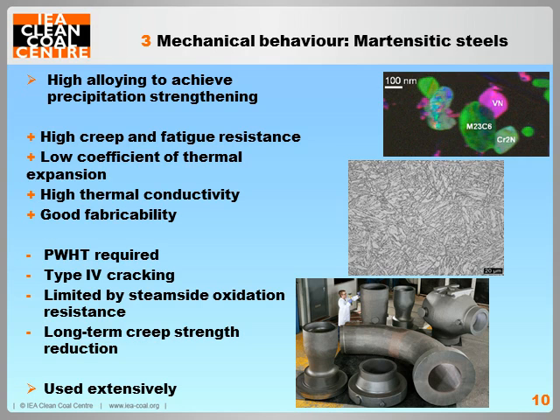Martensitic steels allowed progression to supercritical steam conditions. High alloying of chromium, molybdenum, nitrogen, niobium, vanadium, and others achieve a significant amount of precipitation strengthening. Generally, the 9 to 12% chromium martensitic steels have high creep and fatigue resistance, a low coefficient of thermal expansion, a high thermal conductivity, and good fabricability. 9 to 12% chromium martensitic steels can operate up to 600 degrees Celsius at high pressures